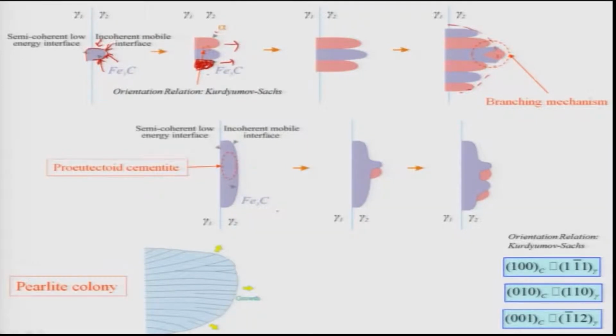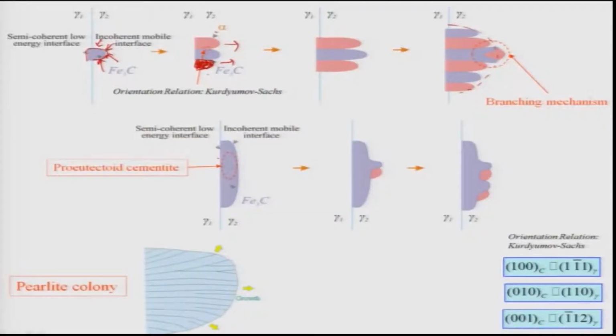Now you can also have alloys which are not 0.77% carbon. They can be hypo-eutectoid or hyper-eutectoid. If it is hyper-eutectoid, you will have a pro-eutectoid cementite. We will discuss how it can happen, because alloys with more than 0.77 weight % carbon will always have pro-eutectoid cementite present. And this pro-eutectoid cementite will be present mostly on the grain boundaries, because grain boundaries are the ones which allow nucleation of these pro-eutectoid cementites, and if it is present there, it will lead to easy nucleation of the cementite for the pearlite.